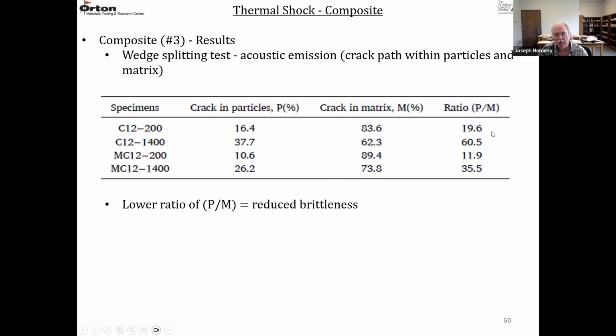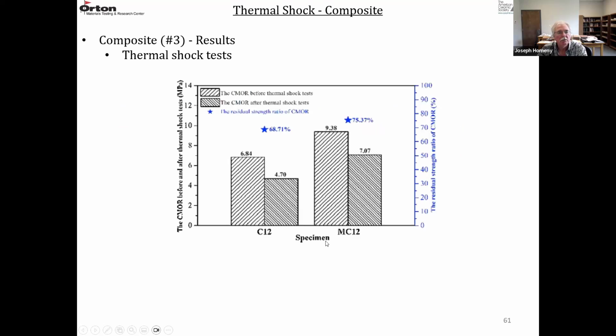So when you look at the ratios, this is 19 at 200, this is 11, this is 60 at 1400, this is 35. So the lower this ratio, the less brittle the material is. So these ratios predict the MC12 is better in thermal shock.